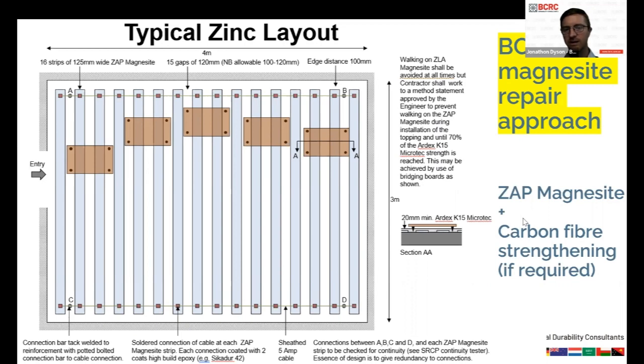So we're finding that the ZAP magnesite system reduces the amount of disruption, reduces the amount of noisy concrete breakout, because you only have to break out the loose and spalled concrete. You can leave the rest of the contaminated concrete in place. You obviously treat the corrosion where it's exposed, and then you install the cathodic protection. And if needed, if some of the reinforcement is so far corroded that the section loss is such that some strengthening of the slab might be needed, then you can potentially add some carbon fiber strengthening to the ZAP magnesite system to fix that issue as well.